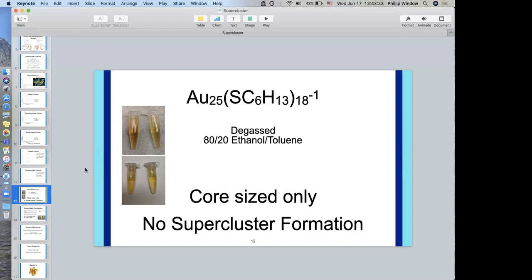In this really small system, the charge state is so important because you have core-to-core interactions right there, and the counterion is so significantly large compared to the core of the nanocluster that it has a huge impact. So I think there are ways that you could mitigate the impact of both of them.